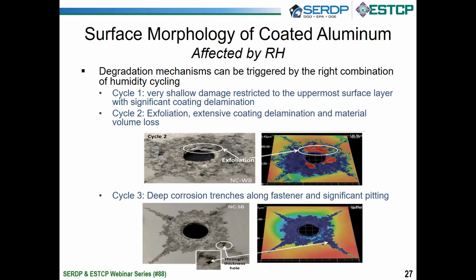So it was small depth of attack with significant delamination. The interesting thing starts happening when you start this cycle 2, where we did not fully dry it. So on the left, you see these digital images, and on the right, you see the digitized images, so actual photographs and then the digitized images.